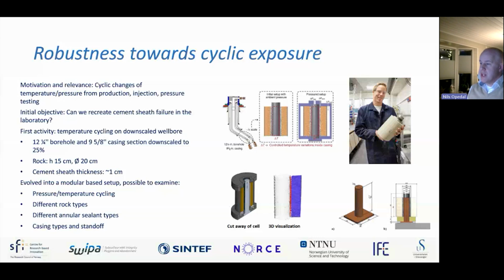We impose either temperature or pressure changes. For the temperature, on the right-hand side, you see a schematic of a copper rod where the sample is placed upon, and the copper rod is placed on a heating and cooling plate where we can generate cyclic changes of the temperature ranging from, I think, minus 15 degrees Celsius up to about 110 degrees Celsius. Likewise, for the pressure, we have a pressure shaft or mandrel. I'm not sure what it's called in English. Anyway, hydraulically, we're able to manipulate the inner casing pressure, where we can again impose different kinds of cyclic stresses from the inside of the casing.